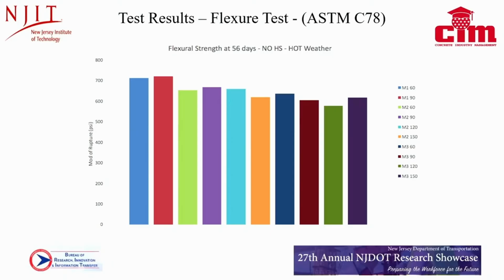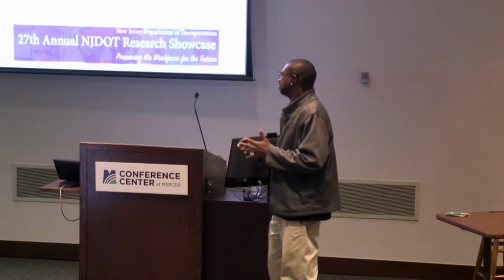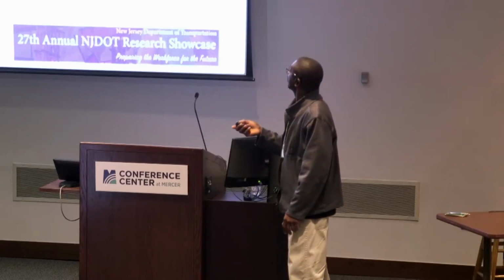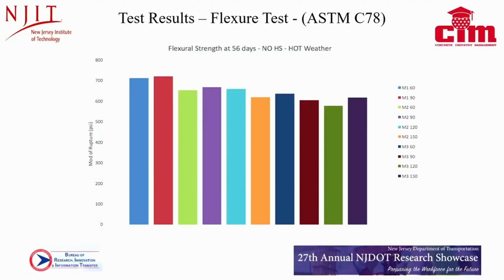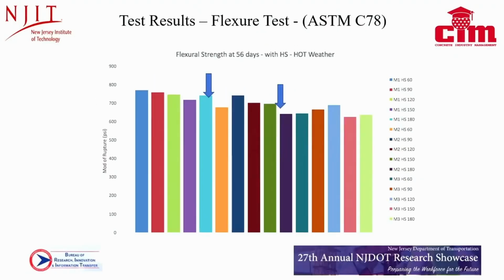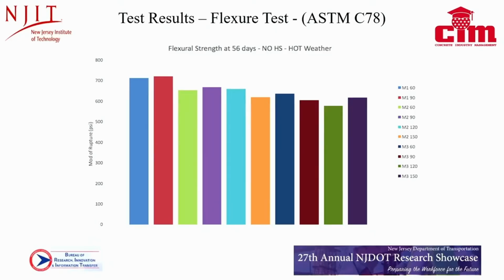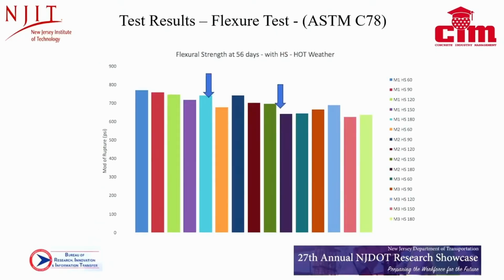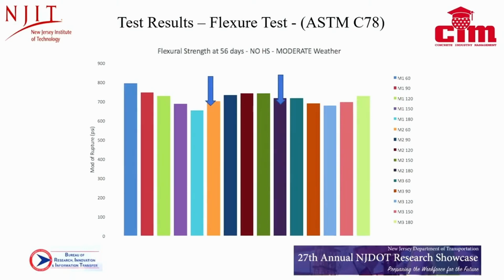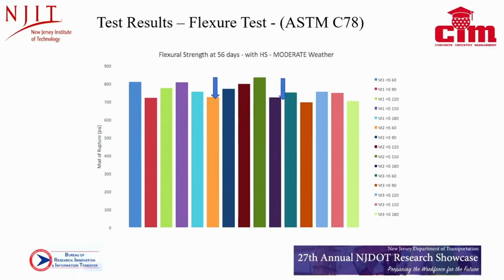So flexural strength is usually about 10-11% of your compressive strength, and we noticed that there was no significant impact on the flexural strength either. So as you can see, it's fairly consistent. This one with no hydration stabilizer. With hydration stabilizer, you see it's above 700 psi. Again, fairly consistent.